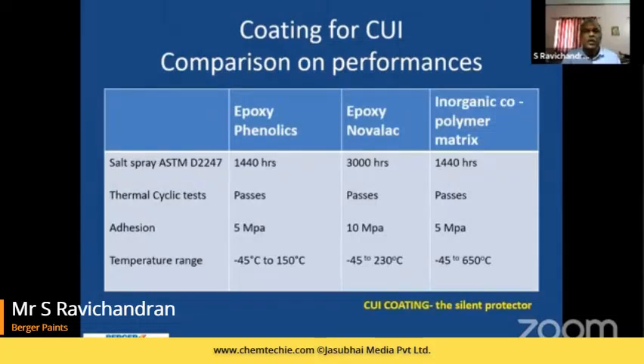A quick review on the coating performances. Yes, the four important parameters are the salt spray resistance, which is far better in the case of epoxy Novolac. Whereas when it comes to adhesion also, yes, it is fantastic. But when it comes to temperature ranges, the Novolacs are better than the phenolics, and the inorganic copolymer matrix are far better when compared to the earlier two.